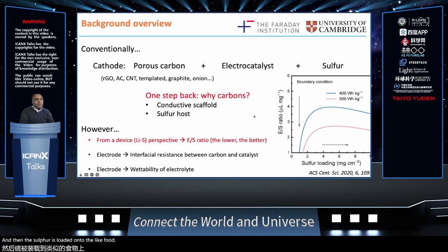Okay. The problem with using porous carbon is that because it's high surface area, and because you want the reaction to occur in every part of the sulfur that's on the porous carbon, one has to apply lots of electrolyte to flood the pores of the porous carbon. And that increases the weight of the battery, but also increases the electrolyte to sulfur ratio. So ideally, a lithium sulfur battery will have electrolyte to sulfur ratio that's on the order of 4 or lower.